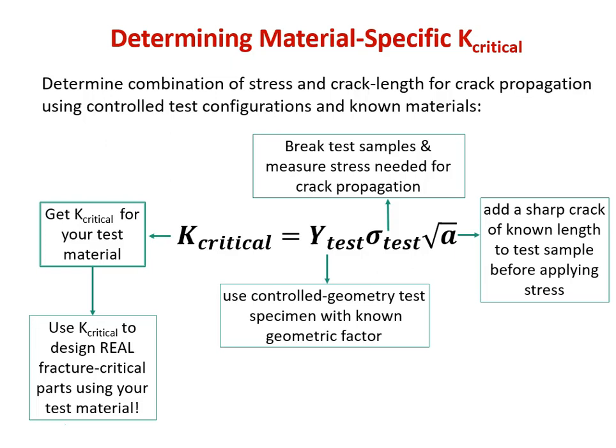So K-critical is specific to the material, and it is equal to a geometry factor times the test stress that was applied times the square root of the crack length. So we actually this time have a material property that is itself dependent on more than just chemistry and processing, but is also dependent on flaw size distribution. This is very different than every other material property we've defined to date. Everything from corrosion resistance to yield stress to elastic modulus, all of our mechanical properties certainly have been specific only to bond state and processing. Now we have something that's specific to that, plus how big is our largest average flaw, or how big is our largest flaw most specifically.